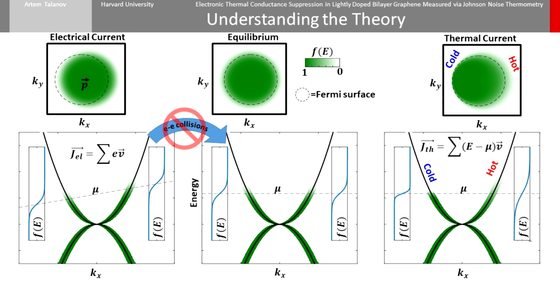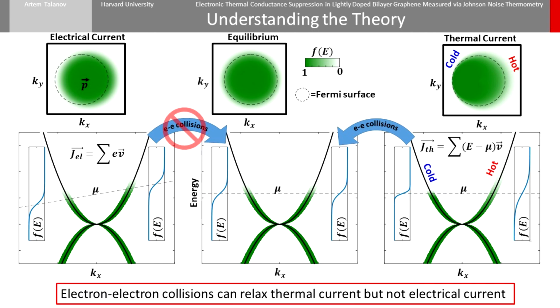To zeroth order, ignoring thermoelectric effects, this thermal current has no net momentum, thus electron-electron collisions are able to redistribute the individual particle occupations to relax the thermal current while conserving total momentum. Of course, the presence of impurities or phonons will relax everything, but the important point here is that in hydrodynamics, electron-electron collisions are the dominant scattering mechanism, and they can relax thermal current but not electrical current.